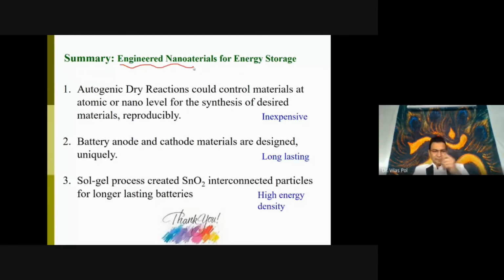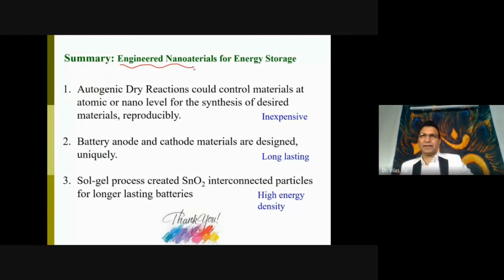So you see what happened, the sol-gel synthesis process that I showed quickly, where the chemical precursor is thrown inside the water, then eventually it made a nuclei. And once you remove the water, you have those nuclei. Let's say those are 10 nanometer particles. Once you dry them off at 100 degrees Celsius, now you have a huge surface area for the typical particle, around 200 square meters per gram. Now, just having the nanoparticle is not enough because they are so fluffy, light in weight. The tap density is very important in the battery. You have to accumulate a lot of material in a smaller pack.